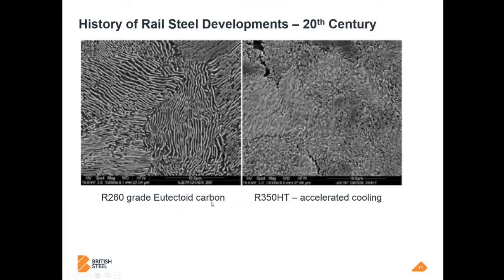It's the workhorse. Further improvements in the late 20th century came from heat treating. So with pearlitic rail steels, if you accelerate cool the rail through the range of about 800 degrees down to about 500 degrees, you can force it to transform at a lower temperature, and it puts more energy into the transformation kinetics, and you end up with a finer pearlite. By cooling aggressively through that temperature range, you can get a very, very fine pearlite, which is harder and stronger with only a minimal loss in ductility. You maybe lose 1% of elongation, but you gain 90 Brinell hardness.